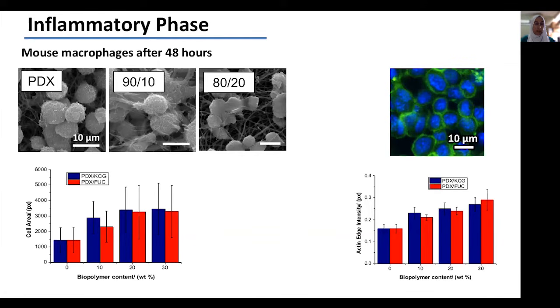And we analyzed the cell area of the macrophages on the different scaffolds, and we found that as we increased the biopolymer content, the cell area was also increasing, irrespective of whether the polysaccharide was kappa-carrageenan or fucoidan. In the next step, we stained the cells in terms of their nucleus and cytoskeleton. So the image on the upper right-hand side shows the fluorescence microscope image of the macrophage cells. In blue is the nucleus, and what is stained in green is the cytoskeleton of the cell. We tried to quantify the actin edge intensity of the cells, and we noted that the actin edge intensity increased as we increased the biopolymer content.